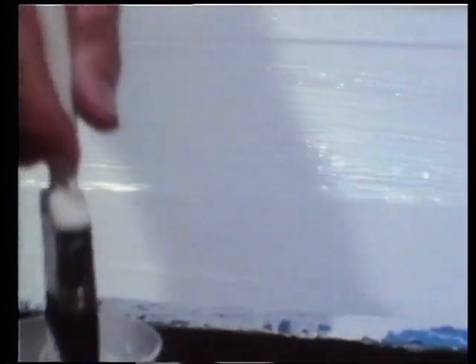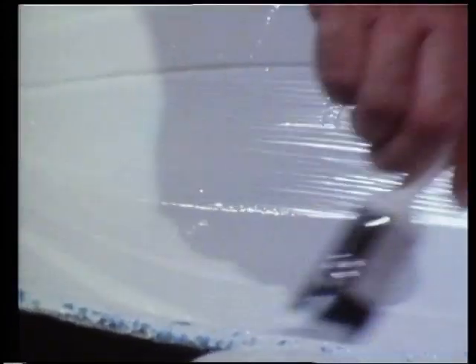The second reason that we use gel coat is to isolate the laminate itself, which contains the glass fibre, from the environment in which it lives. Gel coat is a completely homogeneous layer. It's impervious to penetration by water. It resists breakdown by ultraviolet for a fairly extended period of time. So effectively, it's a completely impervious layer over the outside of the main fiberglass moulding. And of course, the fiberglass itself is what gives the article its strength and rigidity. The gel coat, because it's not reinforced, is really quite brittle.